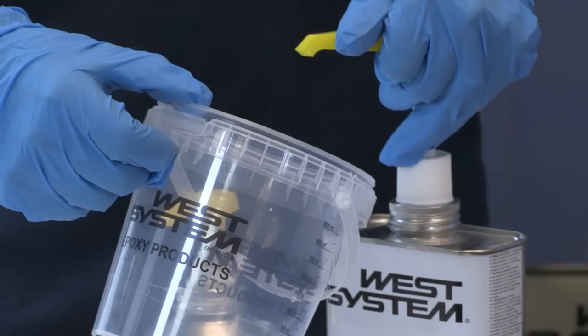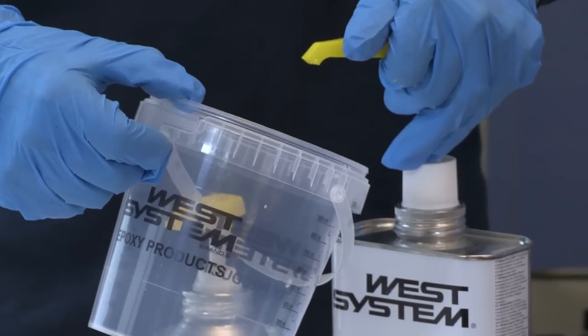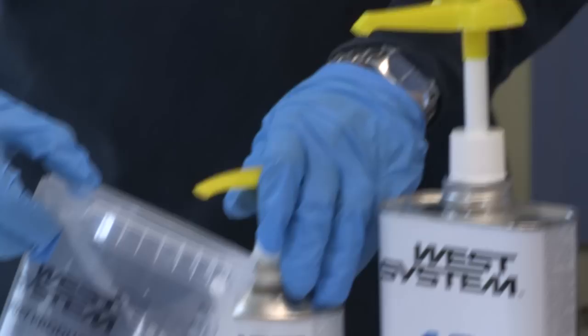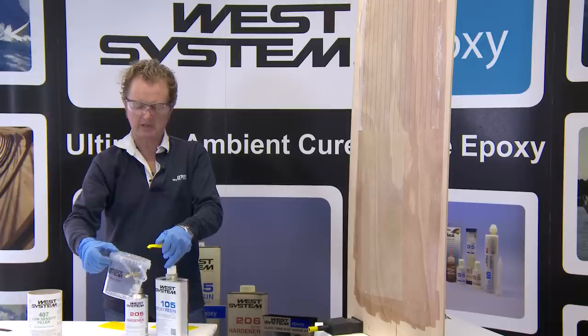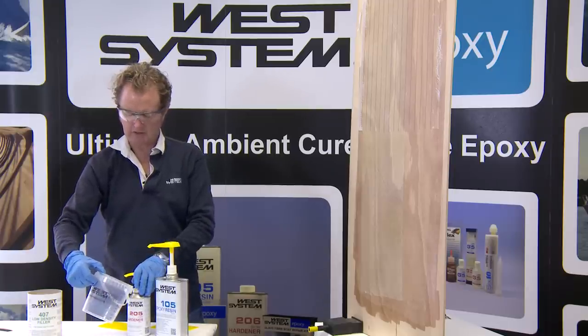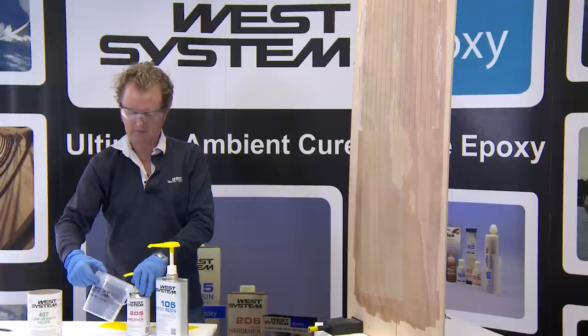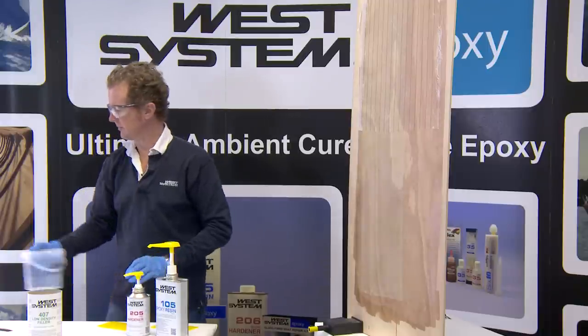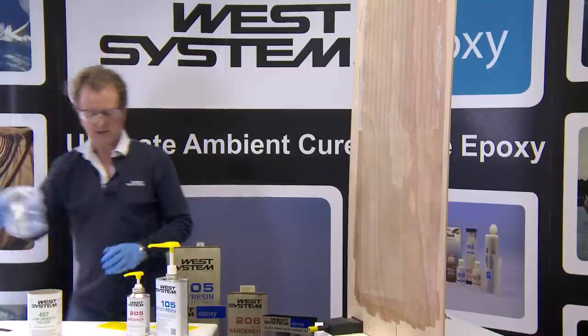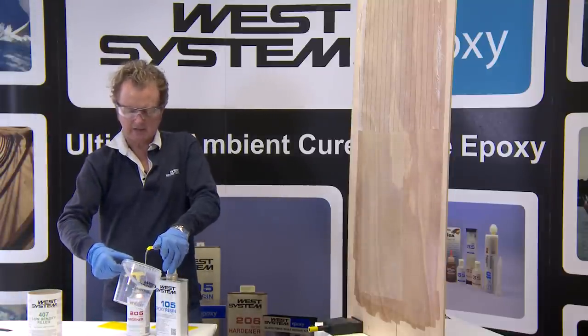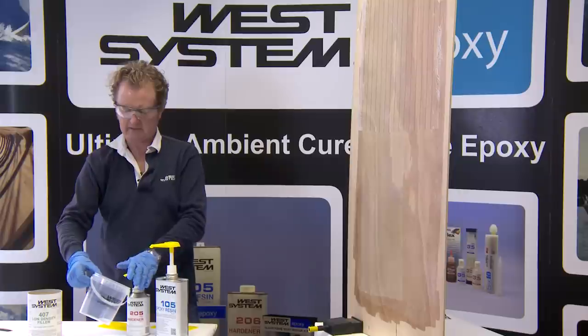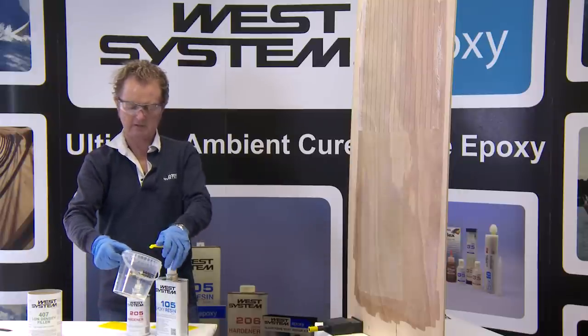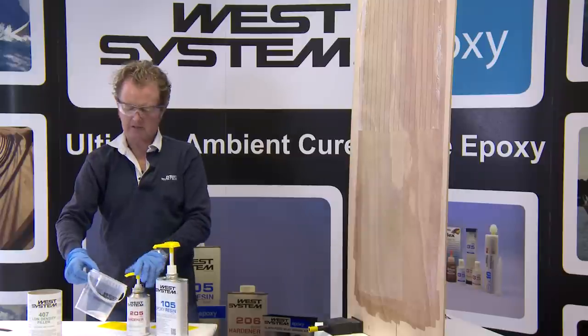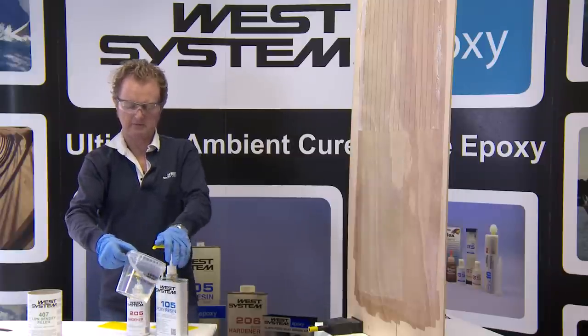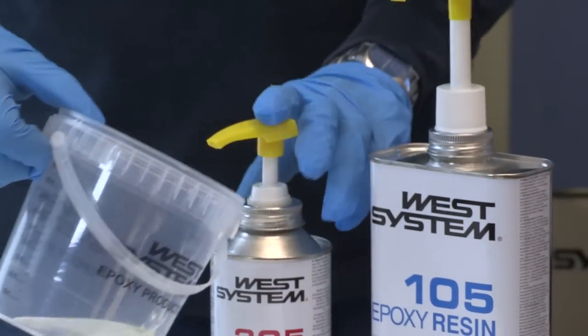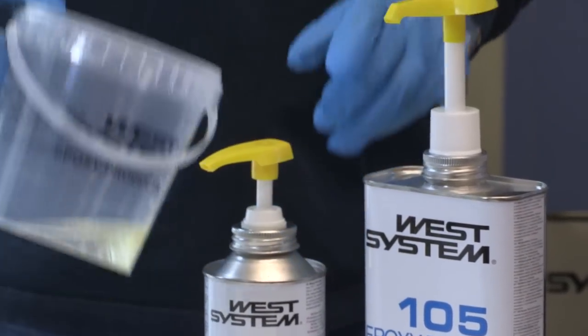The first step is to make sure the pumps are primed. I do that by making sure there's some resistance behind the pump and waiting for a small amount of epoxy resin to come out of the resin pump and a small amount of hardener to come out of the hardener pump. I discard that mixing pot and use a fresh mixing pot. I'm going to meter out 1 pump of resin, 1 pump of hardener, another pump of resin, another pump of hardener, another pump of resin, finally my 3rd pump of hardener.